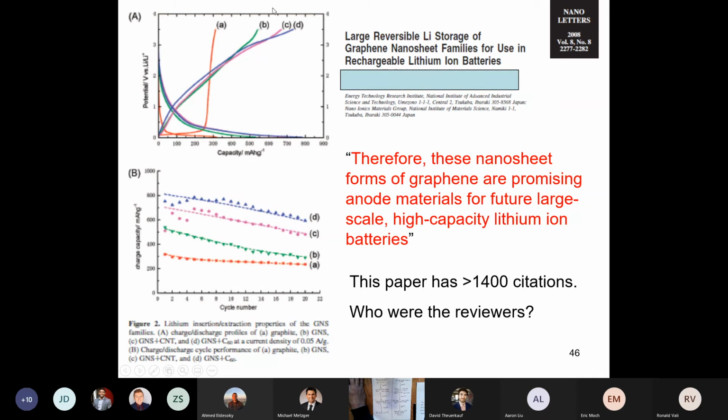So your positive is at 4, say the positive is 4, a flat line. The voltage curve of the lithium-ion cell would start at 4 and end somewhere around 0.7, a huge swing in voltage. Nobody wants that. And also, the energy densities become terrible because the average voltage is only 2 volts. Is that helpful? Yeah, thank you.